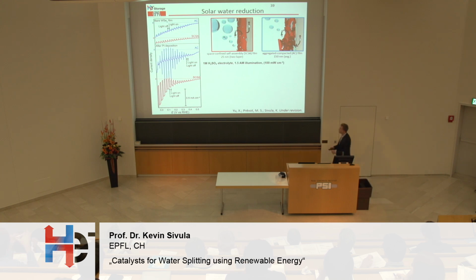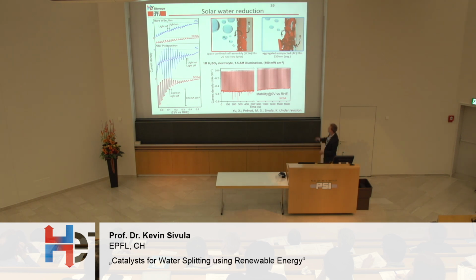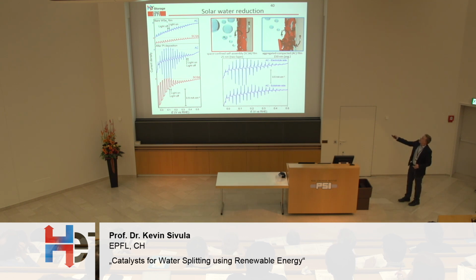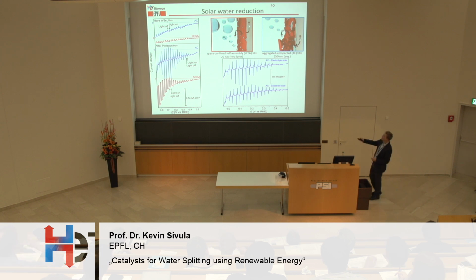And finally, after we put a catalyst on, now I have to admit we do have to put platinum on these, a very small amount, just to get this water reduction reaction to go better, because the tungsten diselenide isn't a great catalyst itself, but we can get about 0.5 milliamp per centimeter squared, which is not so bad considering the way we made these samples, and a stable performance over, well, minutes to hours for these samples without any problems. In fact, we haven't tested them for longer just because we've been too lazy, probably. Finally, we can make some statement about the importance of the self-assembly layer that we've made here as opposed to the aggregation. But I will spare you the details because it's a little bit technical.